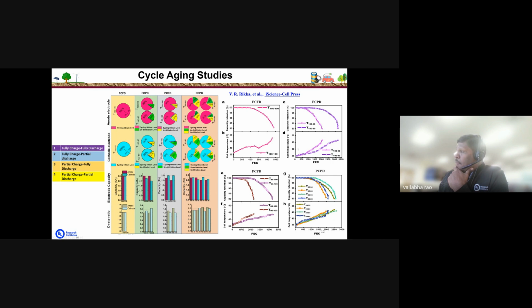But in terms of range, the full charge, full discharge is supposed to give a higher range, because the utilized energy density of this test condition could be higher than that of the other test conditions. But the cycle life is very low. So if we can modify the test condition by mitigating the aging mechanisms, then this test condition can be well suited for electric vehicle applications, and that addresses one of the current demands, range anxiety. One charge for, for example, 300 miles or 400 miles can be achievable by understanding the aging mechanisms of these test conditions. So that is our main interest in doing cycle life studies at different operating test conditions.